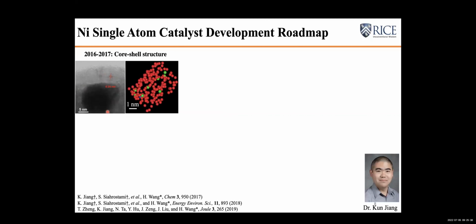It's because this core shell structure has a lot of different site structures inside. You have these nickel nanoparticles, you have the graphene shell. In the graphene shell, you might have some nickel dopants and so on. So where is the true active site? It was challenging at that time. We didn't know whether this is a nickel single atom or so.